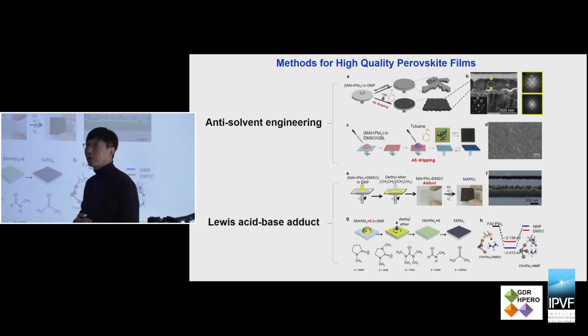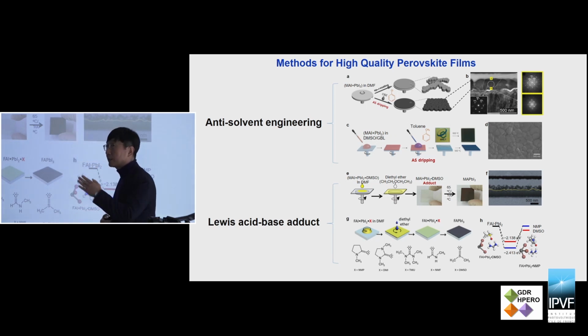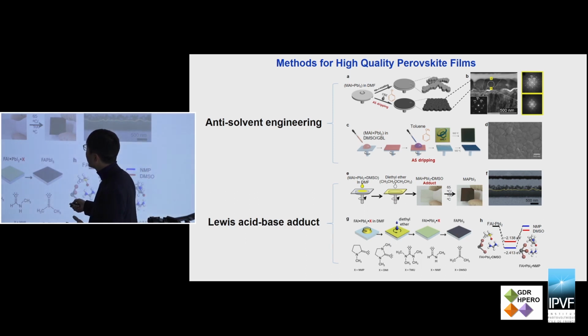So from 9.7% efficiency to 25.2% efficiency, why can we get such high efficiency? Actually, the approaches that contributed to high efficiency are how to prepare a high quality film, and then some compositional engineering. We have two very effective ways to get high performance perovskite films. One is anti-solvent engineering. The second one is the Lewis acid-base adduct.